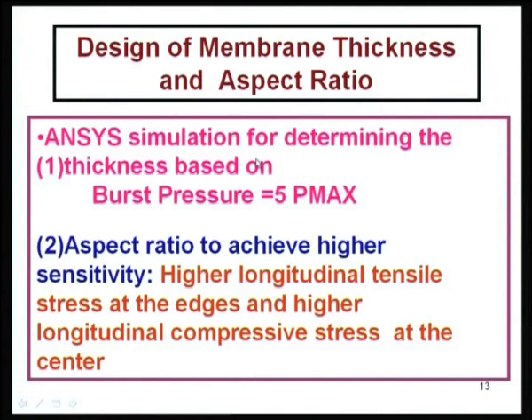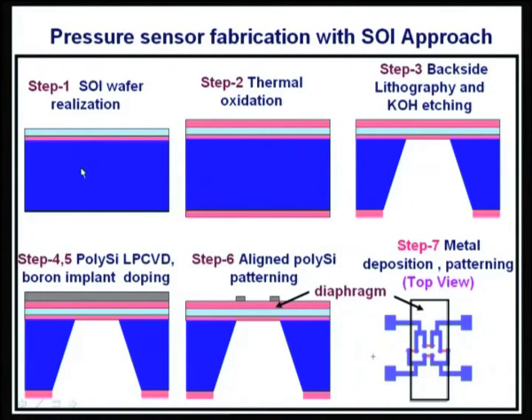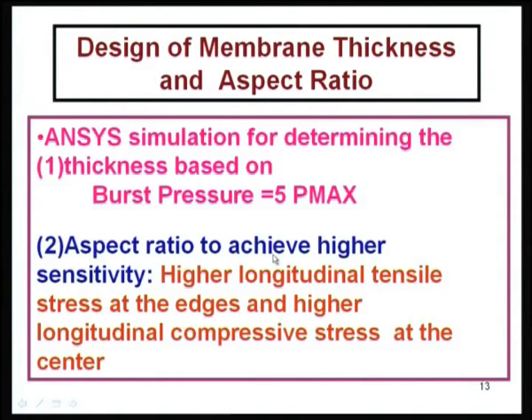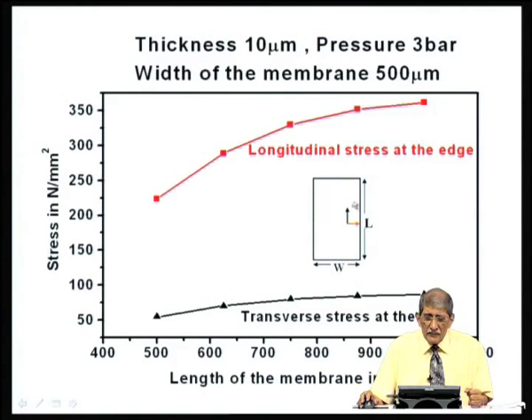Now, the ANSYS simulation. See, the other thing is, in the previous case we were showing a square type membrane. Here we have switched over to the rectangular type of membrane. We have done this because if I make this membrane rectangular instead of square, the stress along this longitudinal direction becomes more if the length of the membrane is more than the width. Both tensile stress at the edges and compressive stress in the middle increase for a given pressure. So, what you want is for a given pressure the stress on these resistors should be more. So, you choose this membrane to be rectangular type.